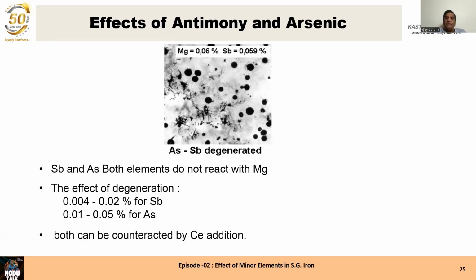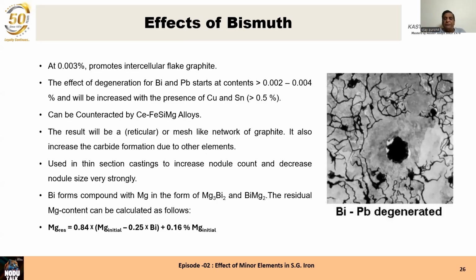Antimony and arsenic are both elements which do not react with magnesium. The effect of antimony and arsenic begins when antimony is present up to 0.004%, and when arsenic is present as 0.01%. But the good point is that the effect of these bad effects of antimony and arsenic can be neutralized by the addition of cerium, which is the rare earths present in the ferrosilicon magnesium alloy. So you have to have ferrosilicon magnesium alloy with some rare earths to make sure that the subversive effects of all the elements which you do not know which are present in your charge mix get neutralized, because cerium does this very effectively.